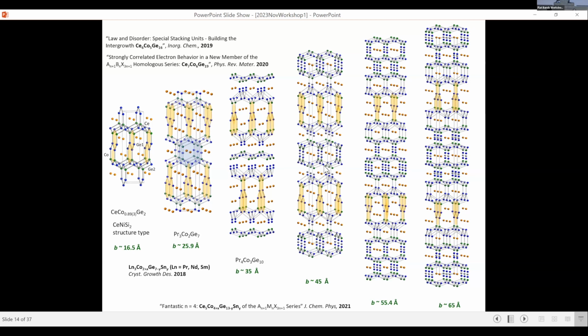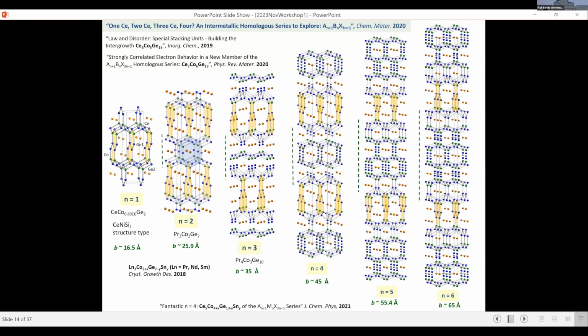And it turns out that with each successive end member, we decided that this is going to be a new homologous series, just like if you think about Ruddlesden-Popper, where you're stacking all these subunits. And actually, we could count the number of BaNiSn3-type structure subunits. So in other words, the infinity member would be the cerium cobalt germanium 3 compound.